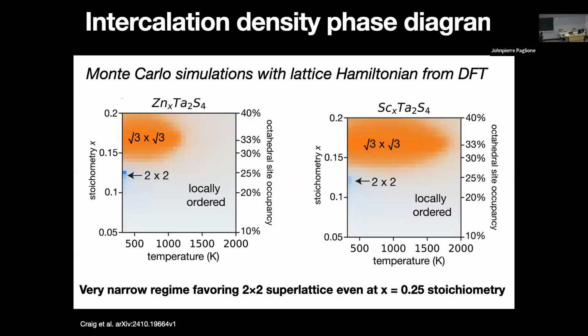So we looked at the zinc and the scandium intercalated compounds, because what we're most interested in is the structural configurations of these intercalants and not their magnetic behaviors. And the DFT gets a little bit complicated if you have paramagnetic ions because it's doing a 0 Kelvin model or computation, unless you use some other methods. So we just wanted diamagnetic transition metal ions, zinc to model a divalent ion such as iron or cobalt, and scandium to model, say, vanadium or chromium.